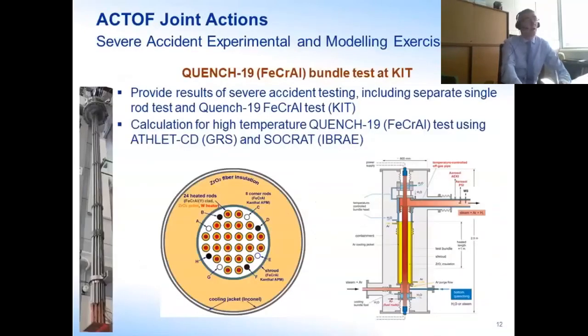And the third work package, as I mentioned before, was the severe accident experimental modeling exercise, which was prepared by KIT, who shortly before our CRP carried out a new test, QUENCH-19, with FeCrAl cladding. It was an international test. Materials were provided by the United States, Argonne Laboratory, and they used these cladding materials in the bundle facility of KIT, QUENCH-19 with FeCrAl claddings. And this data were analyzed using 2 severe accident codes, with 2 participants at that time. We had GRS from Germany with ATHLET-CD, and IBRAE from Russia participated with the Russian code SOCRAT.